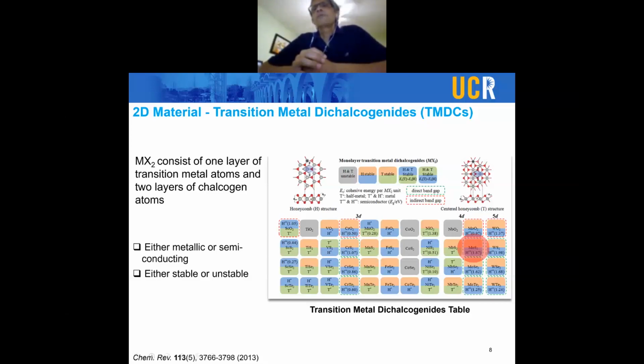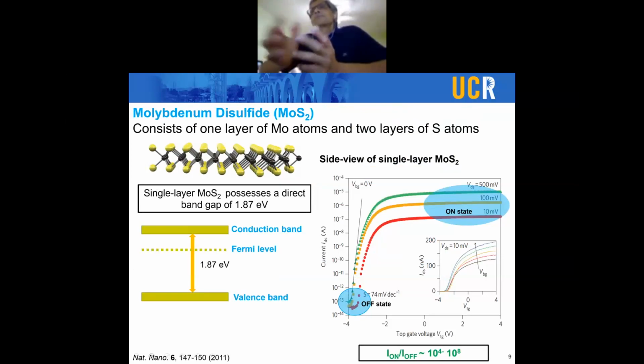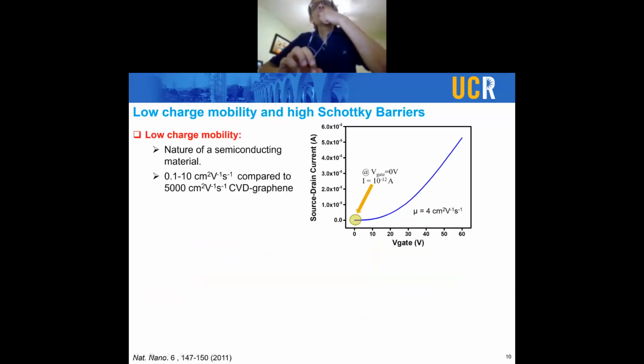And as we investigated the details of the material properties, we found that the issue with semiconductor MoS2 is not going to be resolved by simply using MoS2 instead of graphene. While MoS2 does have very useful and helpful properties of a low band gap, 1.87 electron volt, and a direct band gap, it has a good on-off ratio as shown in that figure on the right-hand side, which graphene doesn't have because of its semi-metallic nature. Unfortunately, it has very high resistance. Its resistivity is very, very high. And so what happens then is that you have very low background signal. So the issue is now that we do get extremely low signal.